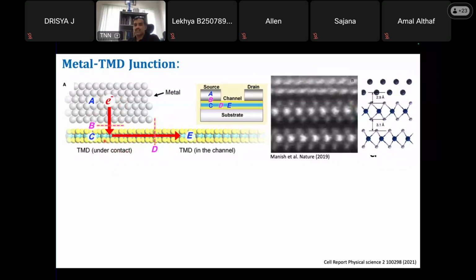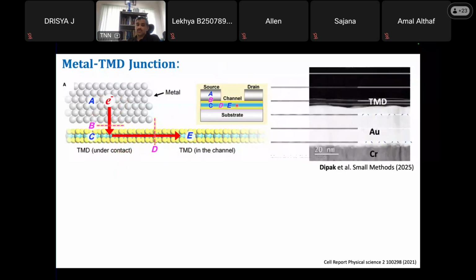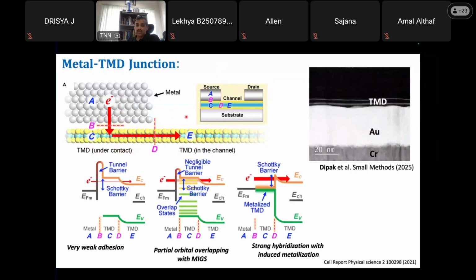And this junction is quite nice because this is the same semiconductor we are talking about. Now, how do we address it when you create a channel of this one? This is a big question, right? We can have a very weak adhesion, or we can have a partial overlapping, because there is negligible tunneling. Partial overlapping means the physical barrier can be minimum, but at the same time, you will have an interaction between the metal and the defects in the semiconductor. Why the defects in the semiconductor?